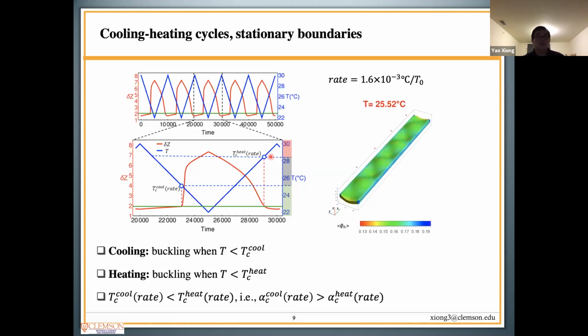So the temperature can be separated into 3 regions. No buckling is observed in the red region during both the cooling and the heating process. In the gray region, the sample shows buckling only during the heating process. And in the green region, we observe buckling during both the cooling and heating processes.